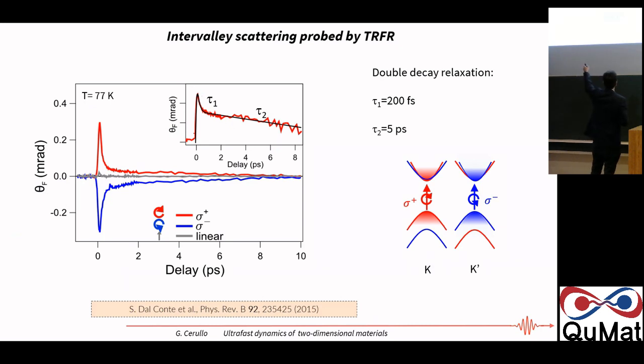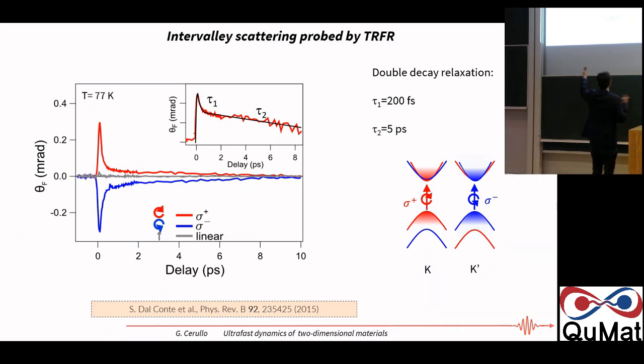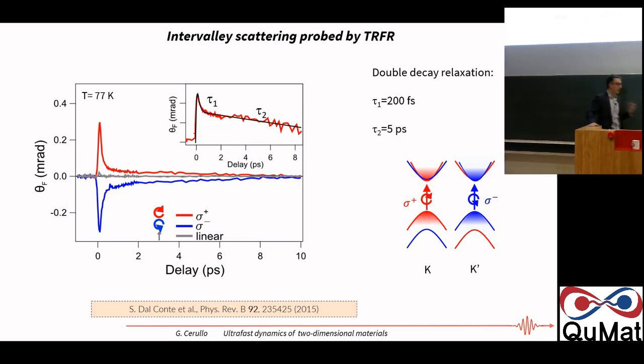And actually, we see here the signal, the Faraday rotation. So first of all, we do a sanity check. If we pump with sigma plus, we see a positive signal. If we pump with sigma minus, we see a negative signal, as we expect. If we pump with linear polarization, which is the sum of sigma plus and sigma minus, we are exciting both valleys simultaneously, so we see almost zero signal, so that's fine. And now we look at the dynamics. So we see that, first of all, there is a very fast relaxation with a time constant on the order of 200 femtoseconds. And so within 200 femtoseconds, most of the valley polarization is lost. We lose probably like 80–90%. And then there is a slower decay with a time constant maybe on the order of 5 picoseconds.